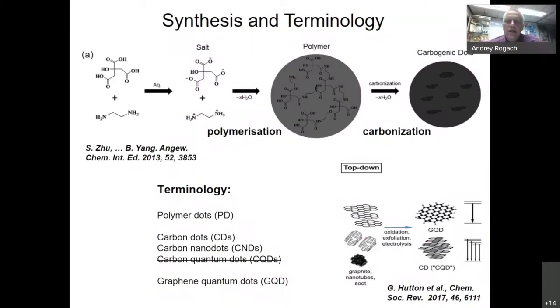But if we make carbon dots, we don't stop at this stage. We continue to heat them up for a longer time or maybe at higher temperatures. And then here we talk about carbonization. So water will go away from this structure, and this precursor framework, polymer framework, will get rid of water and organic nature, and it will become inorganic. So here we call them carbogenic dots, and this can be graphite, really, if they are crystallized. Or it could be amorphous carbon if they are not well crystallized. This is also possible. And then at the end of the day, here we get carbon dots, and we want them to emit light. And I will tell you in my next slides why they emit light. But on the way to these carbon dots, I talk a little bit here about terminology.